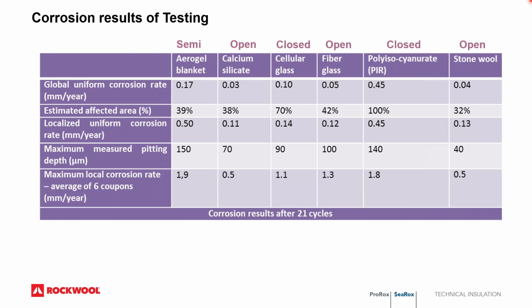Now, when you think of open cell or even semi-open cell, you've got insulation that is literally not bubbles of air. It has pockets of air, but of course these pockets theoretically leak and are breachable by vapor. And that's an important thing to note, because oftentimes when water gets into a system, and it's a hot system, that water will hit the hot surface of the pipe and basically vaporize. It'll boil, vaporize. Now, where does that vapor get to go? In a closed cell, it's still trapped inside the closed cell. But with an open cell insulation, it can permeate the insulation, get through to the other side, because the water vapors will migrate to the lower pressure side of the insulation and then find its way out of the system. And this goes to NACE's comment, where it just basically says the least amount of water in and the fastest way for the water to get out will help mitigate the corrosion. Hopefully that gives you some indication of understanding closed cell versus open cell insulation.